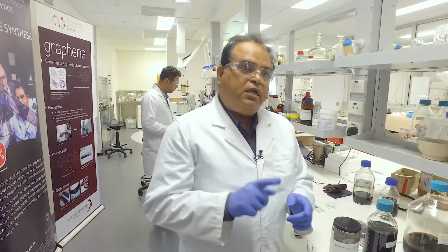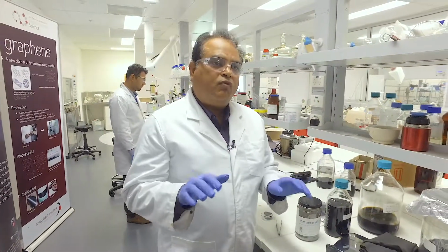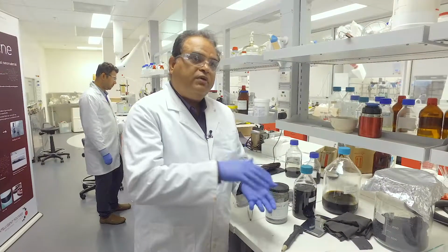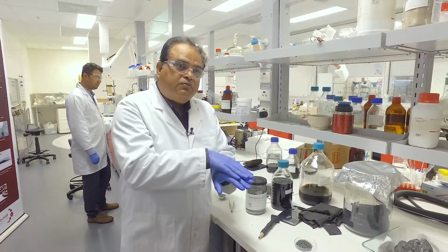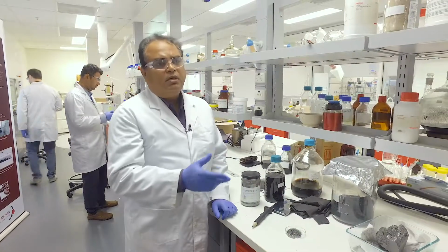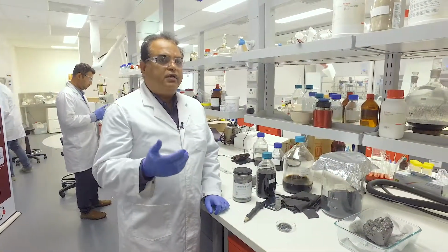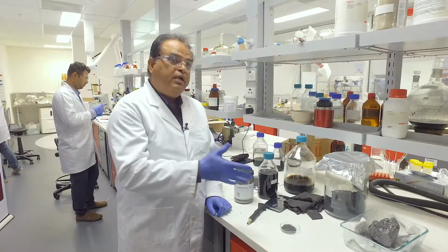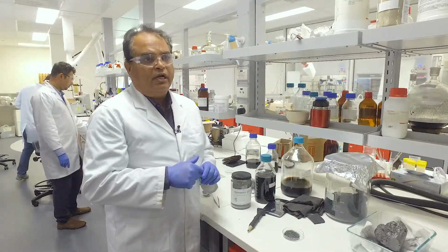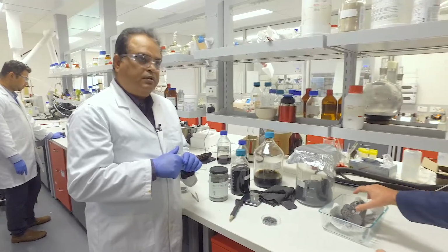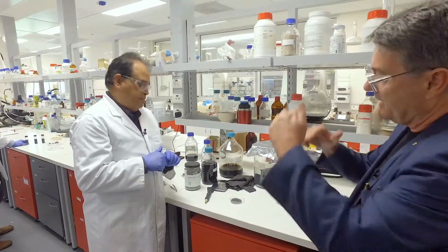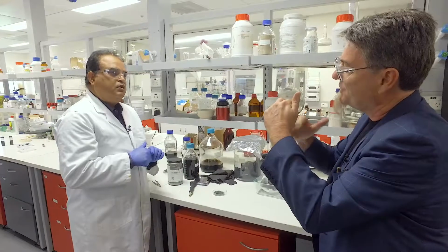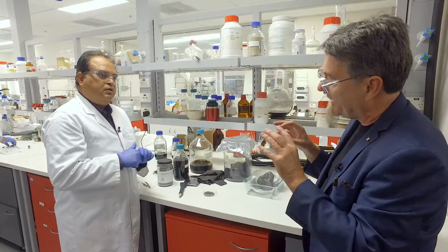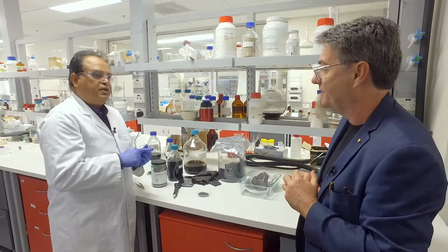And that intercalation involves putting other ions between the sheets of graphene in these flakes. These intercalants need to be of very high boiling nature because they need to stay within the pi space of the graphite. So we have optimized it; orthophosphoric acid, nitric acid, and sulfuric acids are the main intercalants which we have been using for intercalating the graphite. So we take this lump of graphite, we grind it into flakes, and then those flakes have multiple sheets of graphene, and you're putting ions in between those sheets of graphene. Right. Yeah.